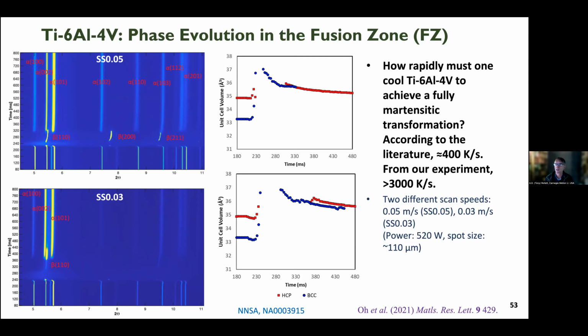This is a classical high temperature BCC, low temperature hexagonal metal. So when you melt it and then refreeze it, you always see this high temperature beta phase. So the question is not which phase appears, as is the case for phase competition situations like stainless steel. It's more about how does that solid state phase transformation happen up around 1000 centigrade, because you have competing approaches.